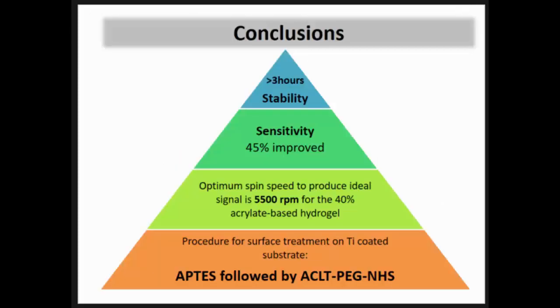So, as my conclusions, we have successfully optimized the procedure to treat the substrates using the chemical APTES, but it needs to be followed by acrylate PEG NHS because our gel is from an acrylate-based polymer. And spin speed also influences the properties of the waveguide signal, so we need to get the desired thickness for a good waveguide signal. And we improved the sensitivity by about 45% and the stability to more than 3 hours.